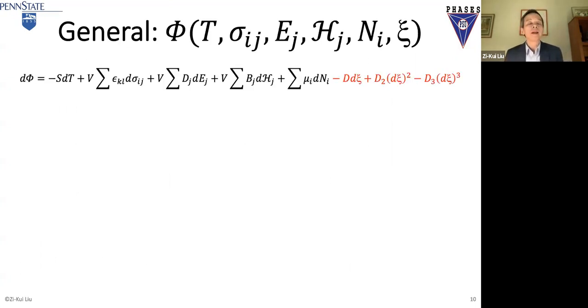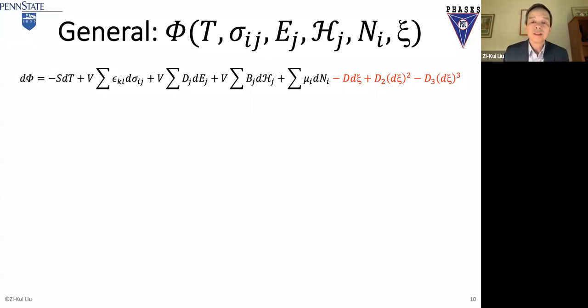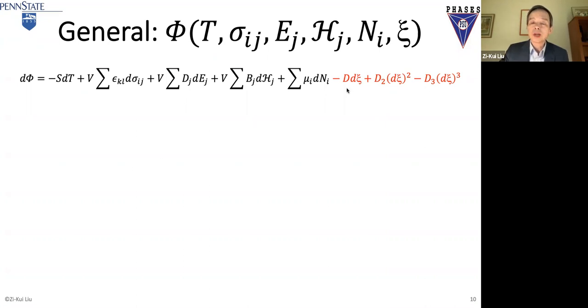That means we really should define a general free energy as a function of temperature, stress, magnetic field, electric field, and internal variables. If we write a combined law for this general free energy, you can see that we have five terms plus three terms for the d-xi contributions. In previous equations, we only had the linear terms, but we could have higher-order terms too, and these higher-order terms play important roles in the behavior of the system.